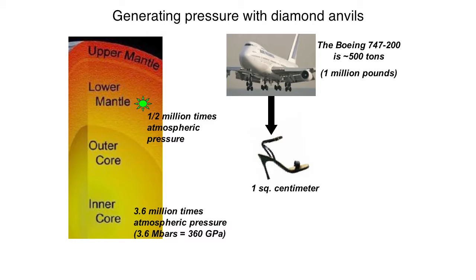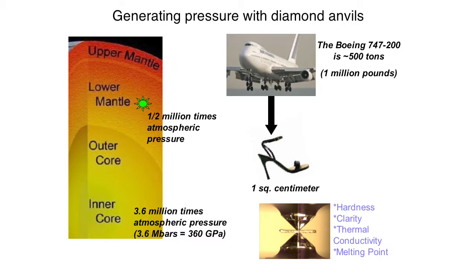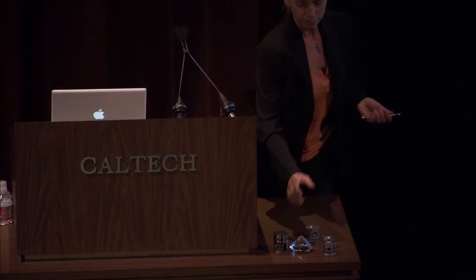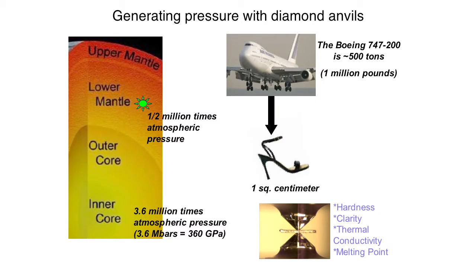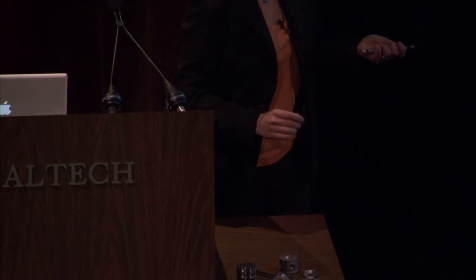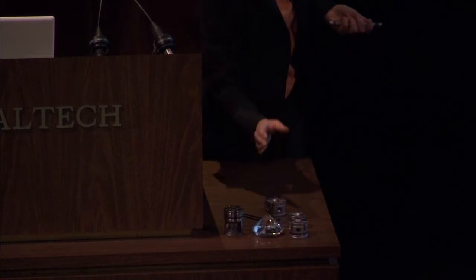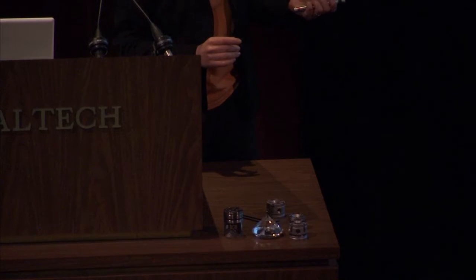So what we use is a diamond anvil cell. It's a small compact device, and I brought several of them here, and different designs are used for different experimental probes. And this is an enlarged anvil, of course, but we essentially take very small anvils, which are about 1/4 carat, and oppose them, cut off the culet, and place the sample on the culet with a metal belt around it. This is also called a gasket.